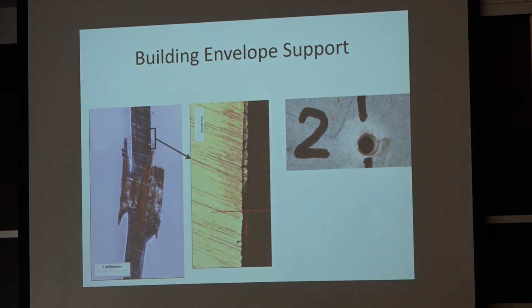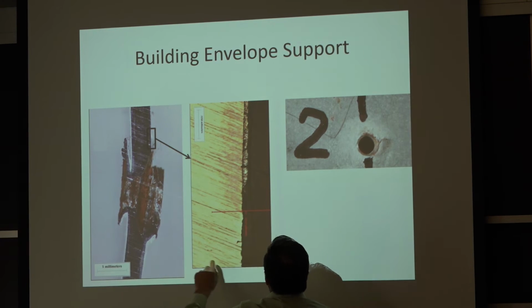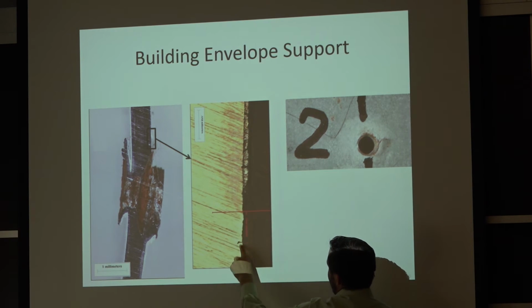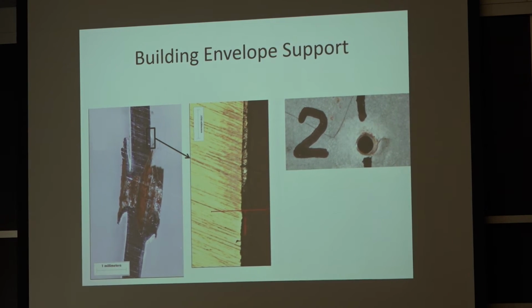This is an example of exactly just that, taking the sheet galvanizing and putting it in these walls for a very special museum in Denver, the Denver Art Museum. They had a special siding that they were putting on that they needed to drive a lot of screws in. So you have the sheet of steel here. You see that there's a fastener that went through it. And what we're looking at is this layer, that's the galvanizing, and you don't have the galvanizing next to the hole after just 3 years of service.